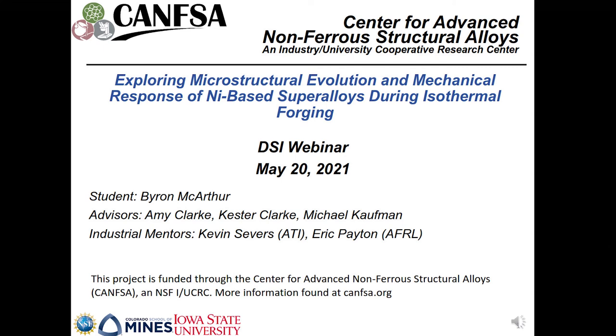And from what I've seen, it does appear that these strains and strain rates are achieved at these temperatures when you do have abnormal grain growth in service conditions. And from the feedback that I've received from industry processors that do this for actual components, as well as DOD advisors, this is within that regime where they're observing this as well. And the published literature that's more open source seems to support that as well.